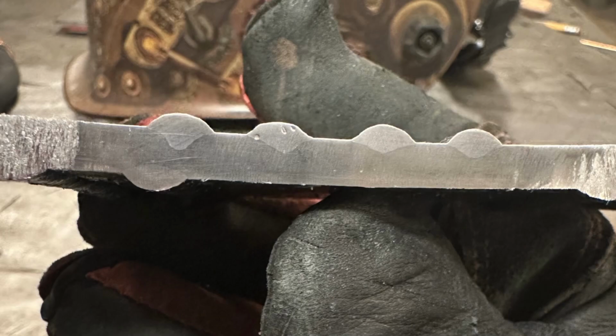So I mirror imaged this so it would line up just the same as the other one. The first pass, which was done on a cold plate, you can see pretty massive penetration for not running values that are suitable for 1/4 inch. Now I increased the voltage by a little bit, and the penetration, even though the plate was hotter, really wasn't better. And you can see porosity on the second pass now that you didn't see on the first, and that's just the nature of flux core wire.